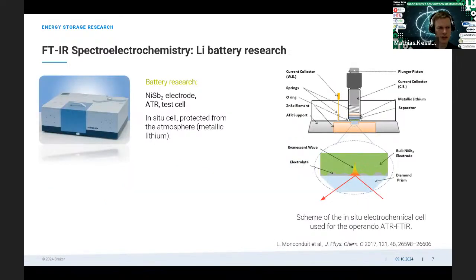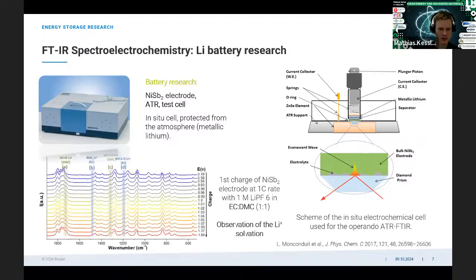And also the second example I want to show to you is related to lithium-ion battery research. And again, we have a cell which is set up on an ATR crystal. And this is now a cell with metallic lithium inside, so it has to be an inert setup without atmosphere access to the cell. And again, we use an ATR crystal on top, then the electrode is pressed, and between the electrode and the crystal we have our electrolyte. And this gives us the possibility to see all the changes of the electrolyte during the change of an electrical potential. And again, we see here on the left side the IR spectrum.